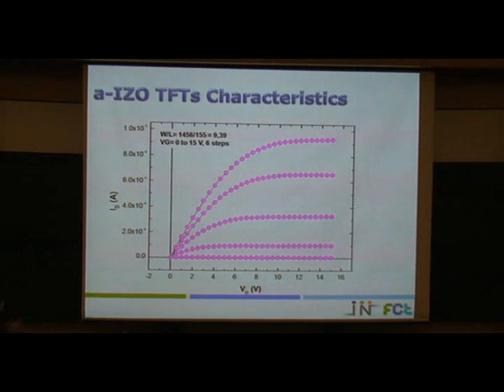And these are typical output characteristics where you can see a very nice hard saturation. So all the curves are parallel, no leakage. Very, very nice. And here is a graphic with the transmittance as a function of the wavelength. As you can see, in the visible region the transmittance, including the substrate, is around 80%. And this is a piece of glass of 2.5 by 2.5 centimeters with several TFTs on it. Of course we cannot see them, but they are there. The transmittance of the full device is around 80%.